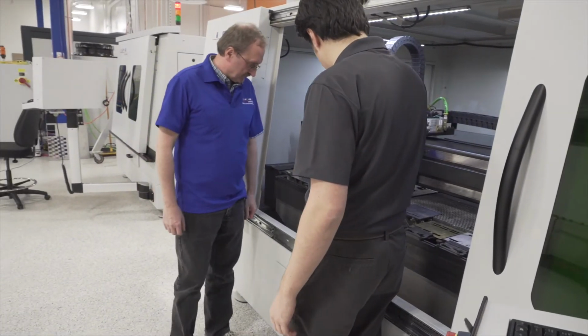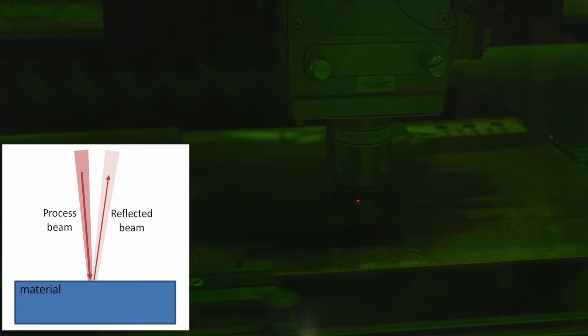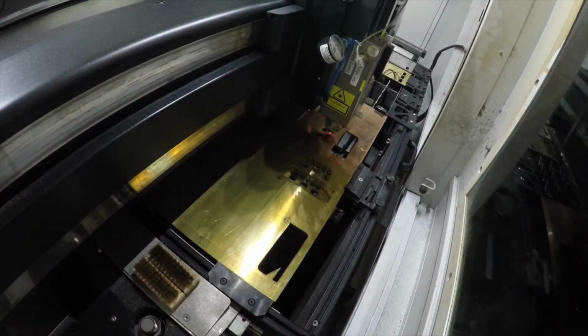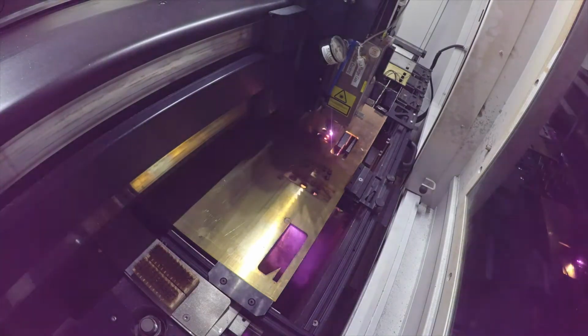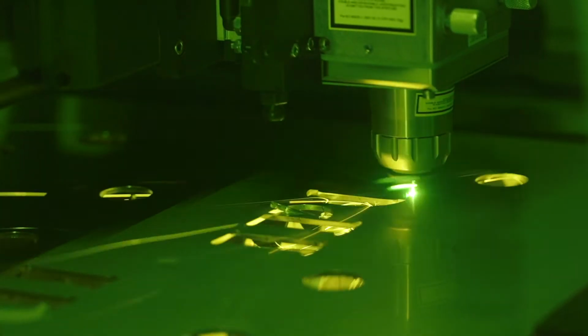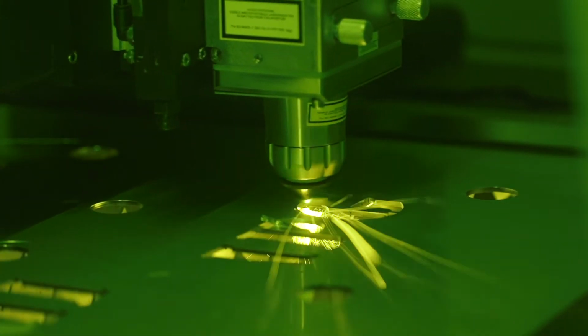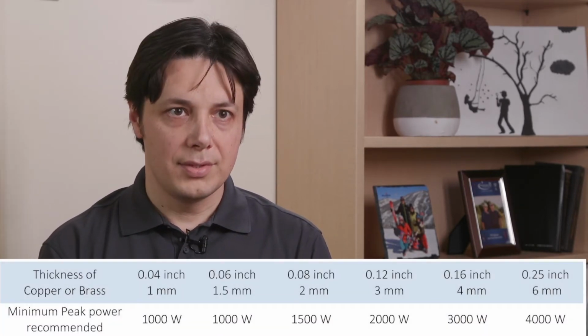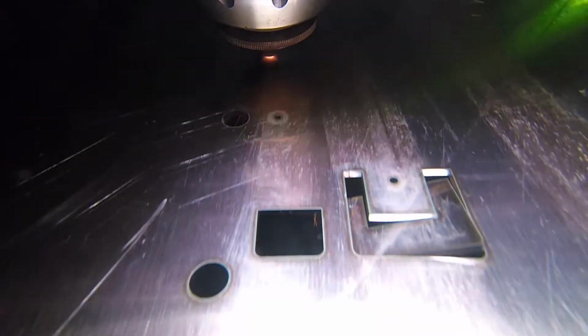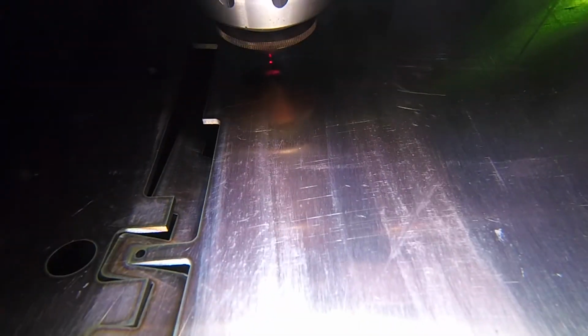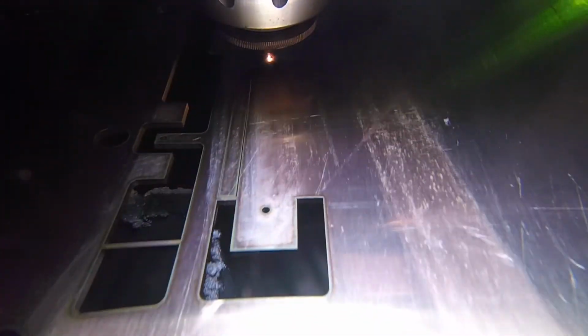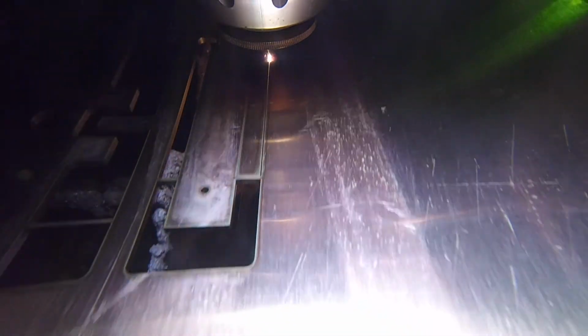So with the right choice of the laser, optical setup, and process parameters, you can quickly melt the surface of these metals and prevent the excessive amount of laser light back reflected and not being absorbed. The excessive back reflected light leads to the inefficiency of the cutting process and potential impact on the optics or laser source. You want to use the maximum peak power that the laser can accommodate to create the highest peak power density on target. Also, for cutting speed, you want to back off 10 to 15% from the maximum possible cutting speed to be in the safe process window margin.